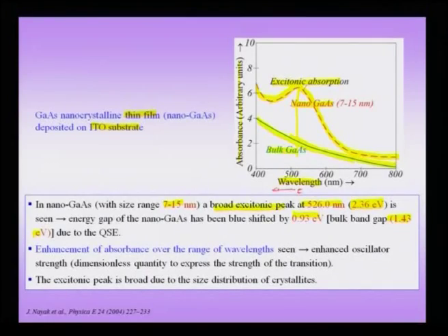And we already know that if you are talking about true excitonic absorption, then that has to lie within the band gap of the original semiconductor, and therefore that would actually lead to a reduction in the band gap. So, we can understand this not as excitonic absorption, though the terminology is used, but as purely coming from the confinement effect and increasing the band gap.